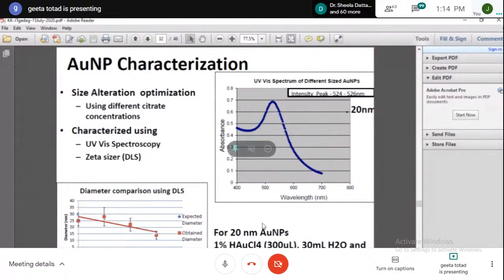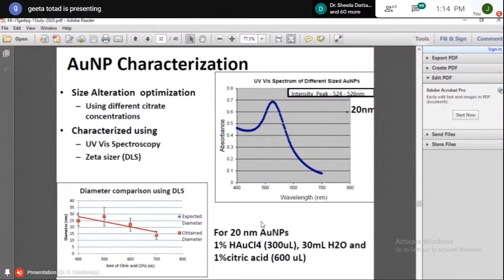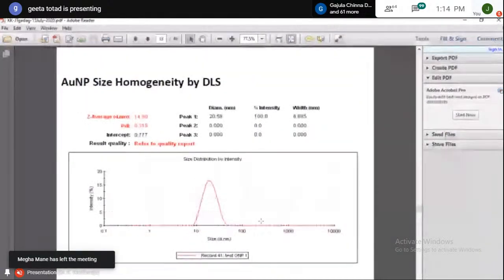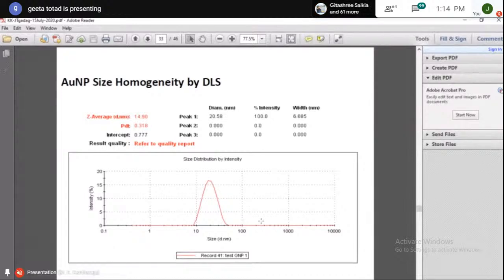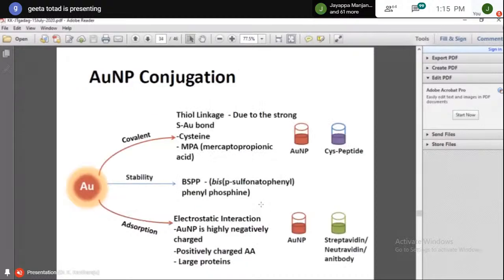This is what is on the left-hand side; you can check it. By varying the citric acid, you can get different sizes of nanoparticle. We checked whether the homogeneity of the nanoparticles we prepared is good, because that is utmost. I think material scientists talk about homogeneity as more important, even for semiconductors. Similarly, we need a very unique, homogeneous nanoparticle for our purpose. Taking all this into consideration, we did it.